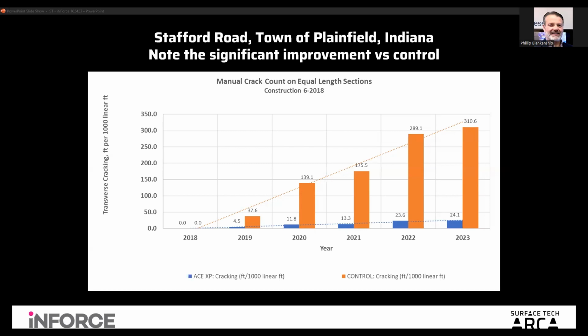But when we went out to look at it every year, you're looking at what the cracking is doing, and the cracking continues to grow as you see from year to year. Going out usually in about April or May to look at it after you get through the winter time. But when you look at that little blue bar at the bottom, you barely see any cracking at all happening. And as an eye opener, I sort of threw a trend line on there, and I don't have an R squared or anything, but it gives you an idea very quickly on the crack rate when you're going from one year to another.